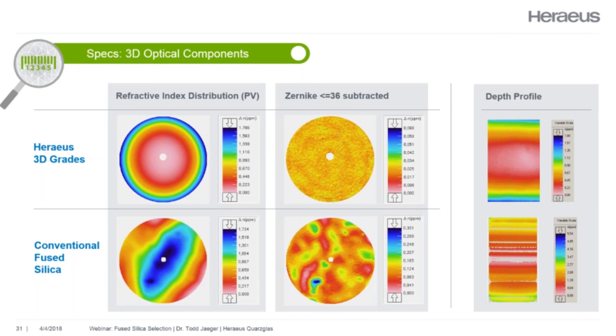Okay, we will continue on with the 3D optical components then. So on this slide here, we see interferograms. At the top left is our Heraeus 3D material grades, and at the bottom is a conventional or as produced fused silica. Now, as mentioned before, if we look side on, not just in the functional direction, you'll notice that the 3D material is homogeneous even in the side on. Whereas your conventional or as produced is going to have layers from the deposition process. Now, as mentioned earlier, Heraeus has invented a unique process of material homogenization that washes out the steep refractive index gradients. In this process, the striae are removed from the material. Heraeus materials are radially symmetric, which leads to the defocus or power being your main contributor when it comes to the Zernike terms. But anyone who's an optical finisher knows that power is one of the easiest things to remove in a polishing process.